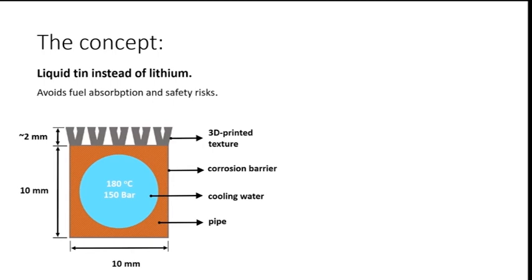We have picked 180 degrees Celsius to keep our metal liquid on top, and 150 bars to avoid boiling. And then on the top, there is this 3D printed texture. That is where the liquid metal is going to be loaded in. And we can play a bit with the thickness of that layer. So how does it look in a full component?